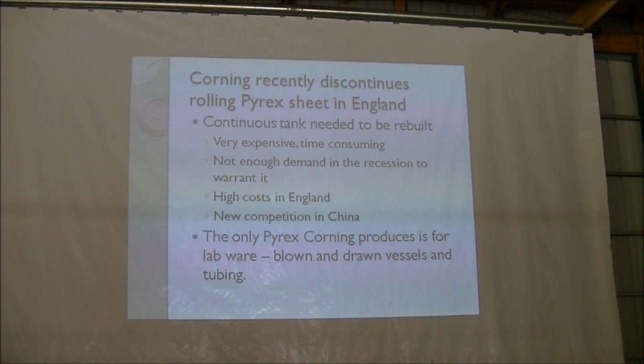When they cool down, you have to chip out all the glass from the tank, break it out. You have to break out foot-thick ceramic brick that lines the tank, and then reline the whole thing. It's about a 2-month to 3-month process. And then you've got to charge the tank, heat this whole mass of tons of sand back up and melt it, and proof it for a while until you finally get the mix right.